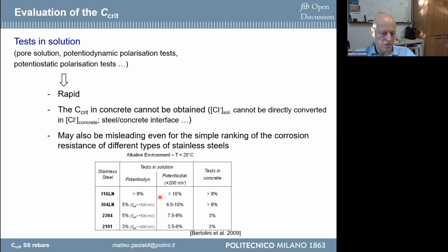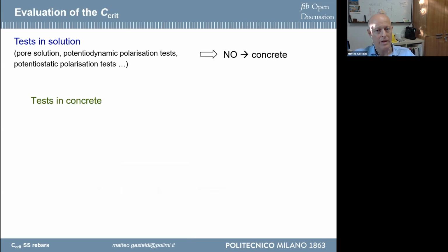And here, briefly, you can observe that, for example, these two stainless steels, one austenitic and the other duplex, seem to have the same behavior in solution because the results are more or less the same. But in concrete you have a very high difference: corrosion initiation in this stainless steel with 3% of chloride, and no corrosion with an amount of chloride of 8% in concrete for the 304L stainless steel. And so this is something that you have to take into account when you consider making testing in solution.